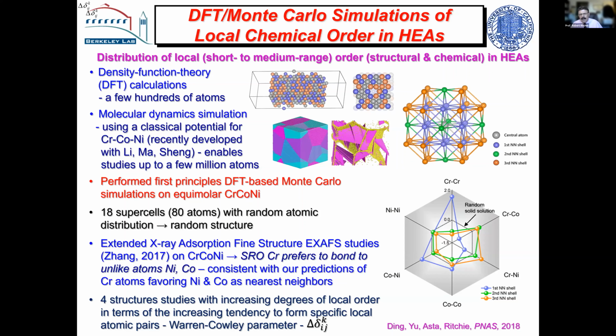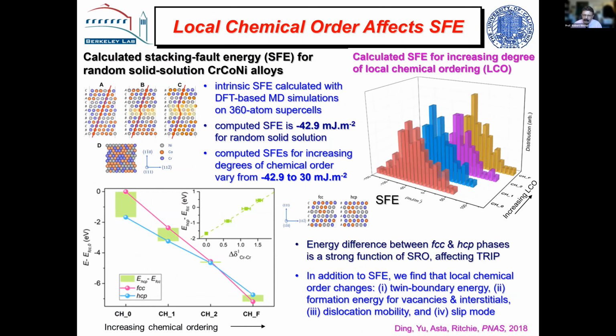And what we found was that the presence of local order will naturally form as a lower energy state. But what effect does it have? We found it had a dramatic effect on the stacking fault energy. Now, this was done for the chrome, cobalt, nickel material. And the computed stacking fault energy for the random solution is actually negative, which is always confusing because anybody who measured it would find it to be positive. And if it was negative, you'd expect the whole structure to be hexagonal, and clearly it isn't. But we found as you increase the degree of ordering, the stacking fault energy went from minus 43 to 30 millijoules per meter squared, which is a big effect.